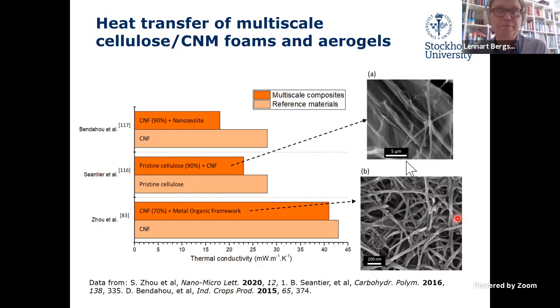This gives some further support for that. If you then start to mix the CNF with another material, you will create heterogeneous interfaces. Here you have CNF being mixed with a zeolite - actually this is cellulose, not CNF, mixed with CNF. So you have a nanomaterial and a macromaterial.